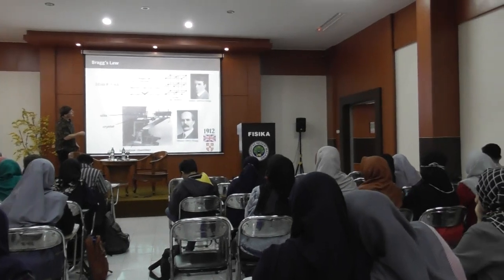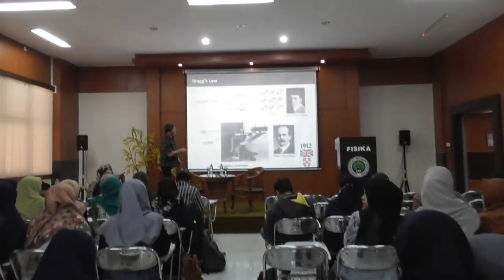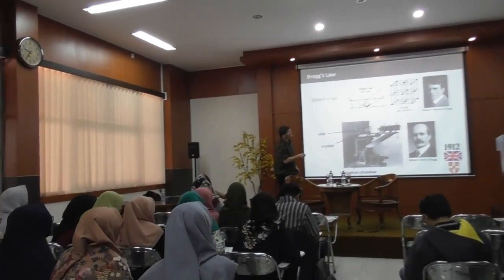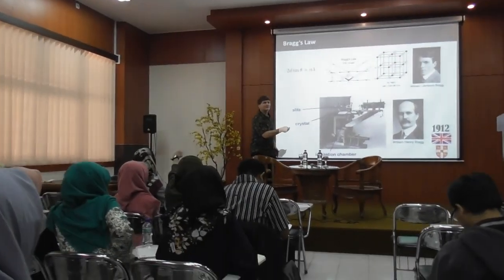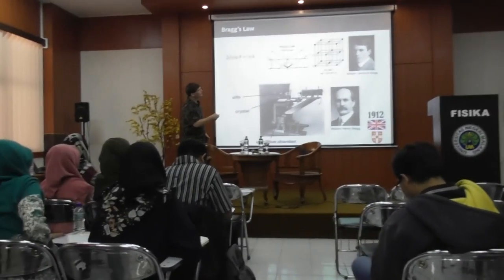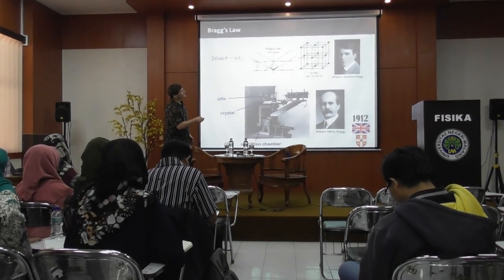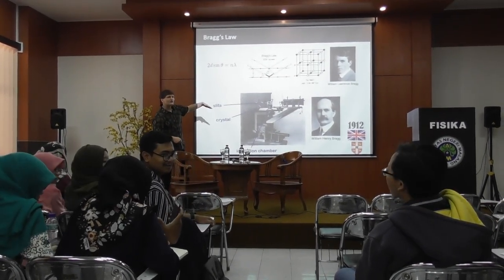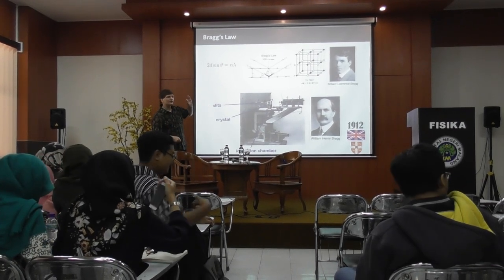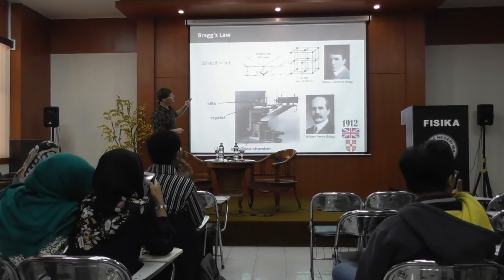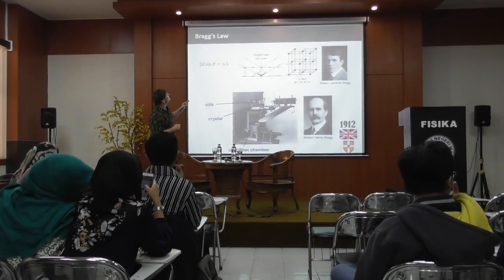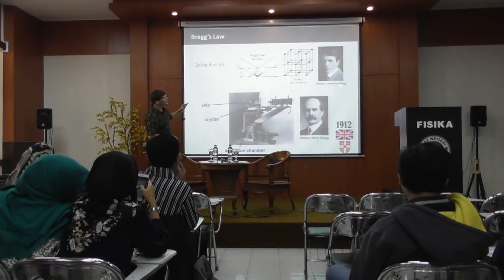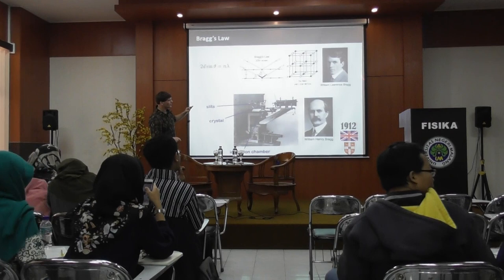Wavelength of the photon coming in. So if you adjust the angle of this crystal, you can constructively reflect a specific wavelength out. Right? So the other wavelengths won't be constructively reflected. So you can tilt this crystal and position it to filter out exactly the X-ray that you want, only constructive X-ray. William Bragg won the Nobel Prize for this in 1915.